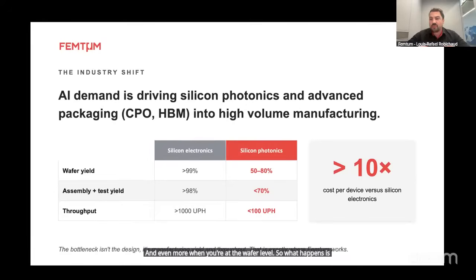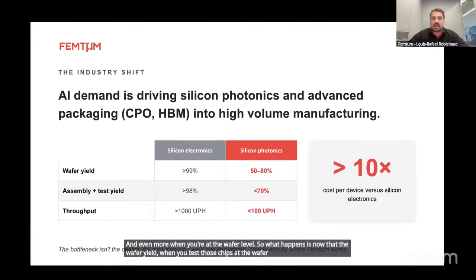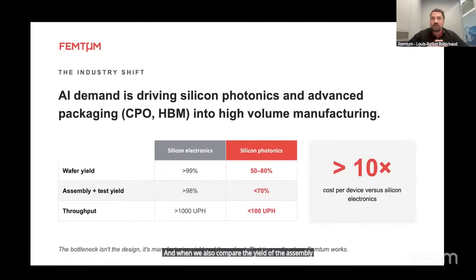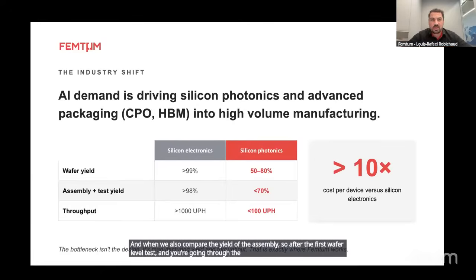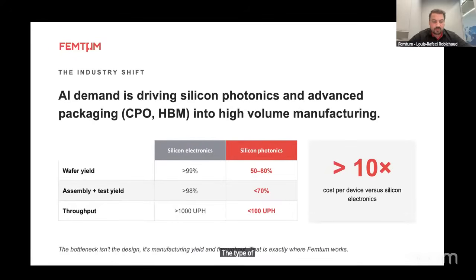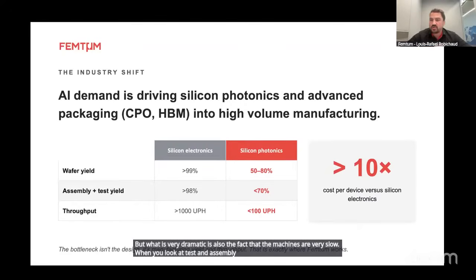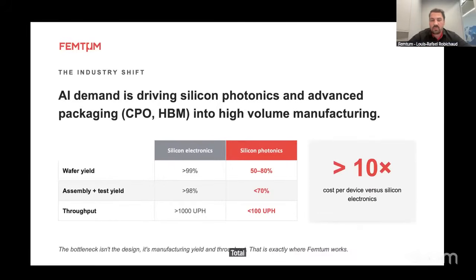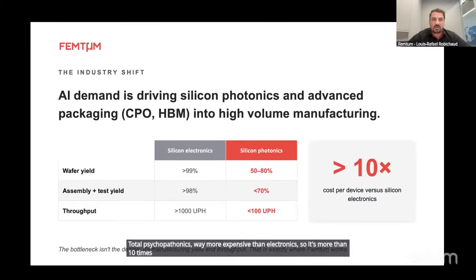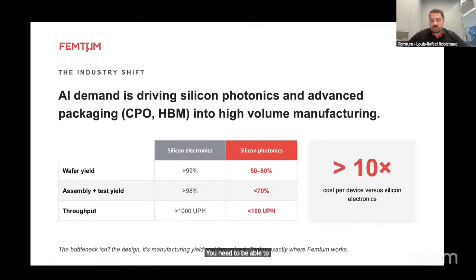What happens is that the wafer yield, when you test those chips at the wafer test, is between 50 and 80% compared to 99%. And when you compare the yield of the assembly, after the first wafer level test, going through the assembly lines and the packaging lines, the yield is up to 70%, and can be way lower depending on the type of photonics. What is also very dramatic is that the machines are very slow. When you look at test and assembly, the UPH, the units per hour, drops below 100. So you have less than 100 units per hour per machine, which makes total silicon photonics more than 10 times as expensive as electronics as we speak. And it's a fundamental thing about the value of silicon photonics. The cost is the denominator here. So if the cost is high, you need to be able to solve the manufacturing yields and throughput.